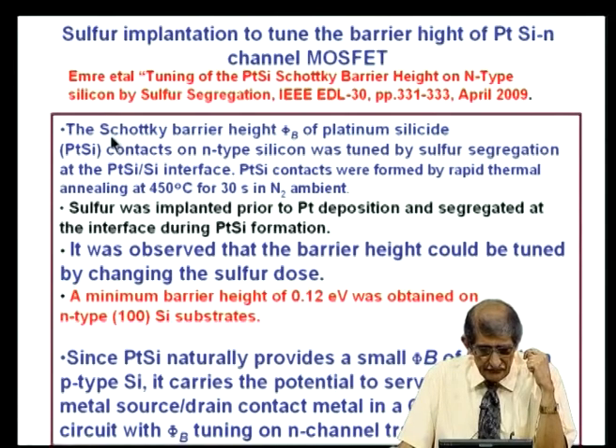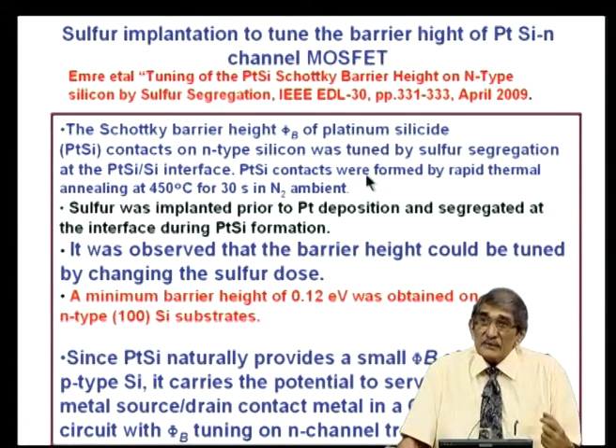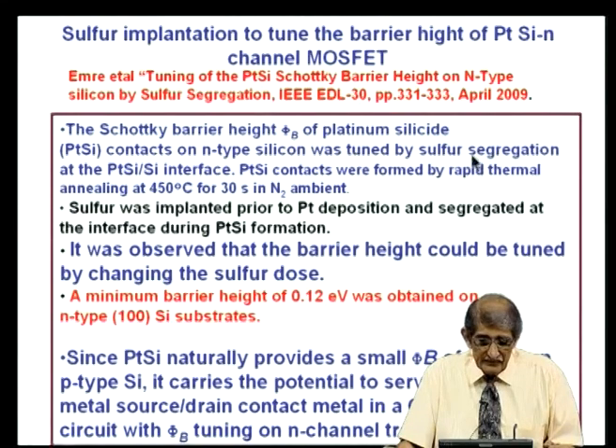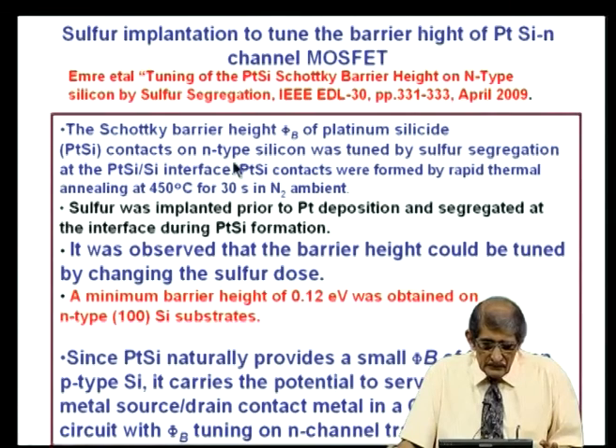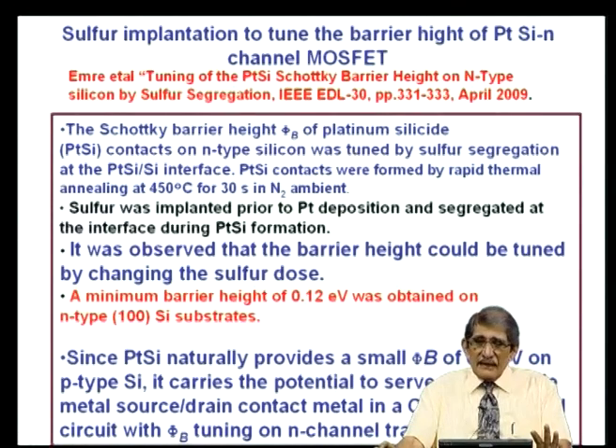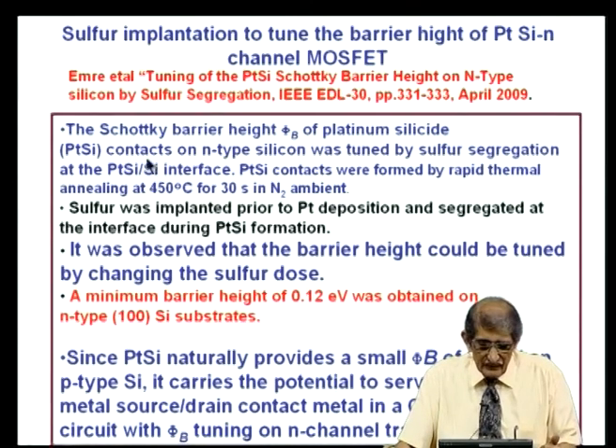So, the Schottky barrier height ΦB of platinum silicide contacts on n-type silicon, you can tune that. If you can tune that barrier height by using sulfur as a passivation, or implanting sulfur, you are in business. Let us see how this is done. The contacts on n-type silicon were tuned by sulfur segregation at the platinum silicide silicon interface. Platinum silicide contacts were formed by rapid thermal annealing at 450 degree centigrade for 30 seconds in nitrogen ambient. So, what is done is, take n-type substrate to study this. If you want to make n-channel, you have to take p-type and implant sulfur.